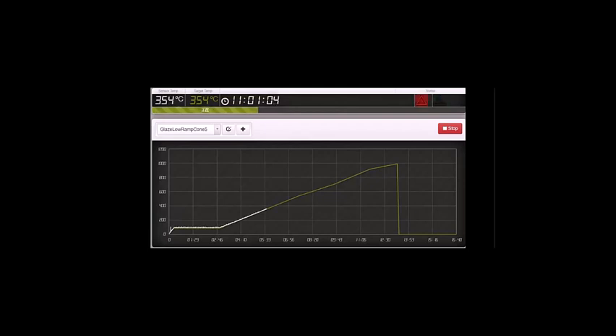The kiln has now been on for about 5.5 hours, and the temperature in centigrade that has been reached is just under 400 degrees. So sensor temperature 355, target temperature 354, so pretty close. The countdown, 11 hours to go. However, it'll be less than that. As I said earlier, the cone will be shutting it off beforehand and then it'll start to cool.